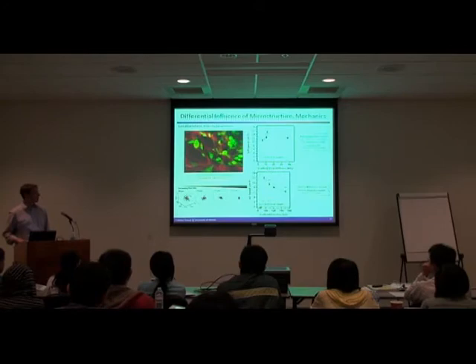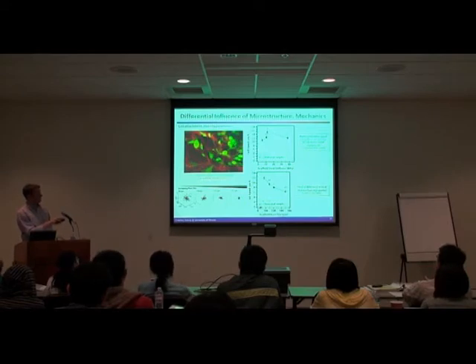So what this is meant to represent is that there not only were there differences in cell attachment as we changed the pore size of the scaffold, but there were huge differences in the motile behavior of these cells. And it wasn't just the total distance that cells moved. We saw relationships with the strut stiffness of our scaffold. We saw this biphasic peak where on soft materials the cells were migrating about 10, in this case 10 microns an hour. As you increase the stiffness, it went up to 15 to 16 microns per hour and then went back down again as you went to high stiffness biomaterials.